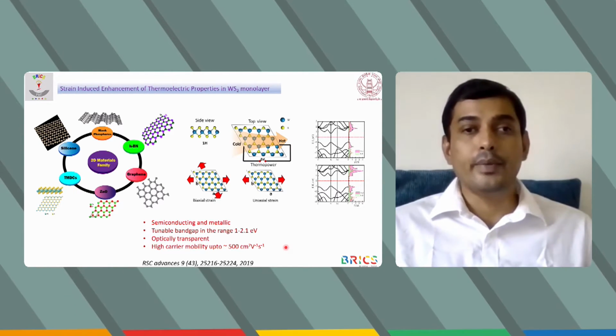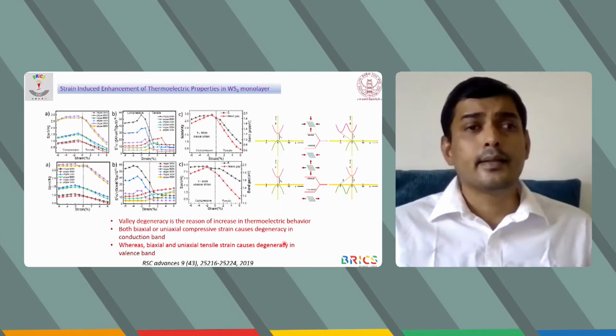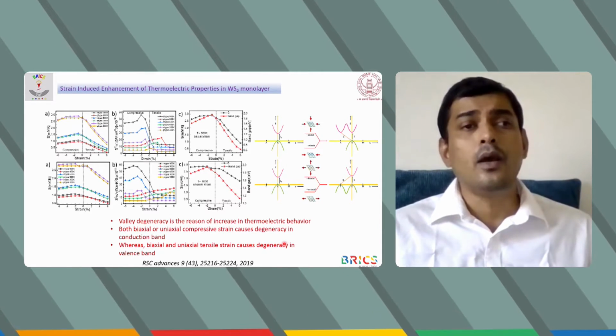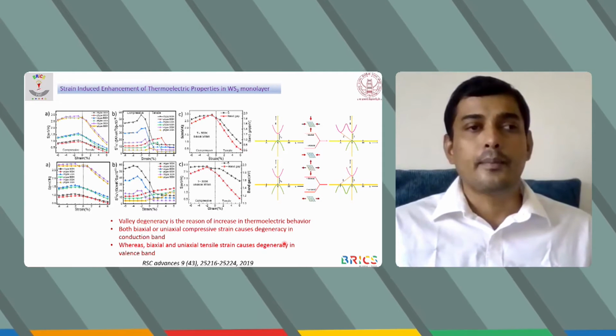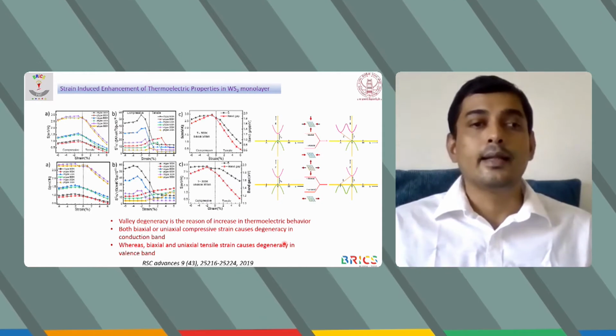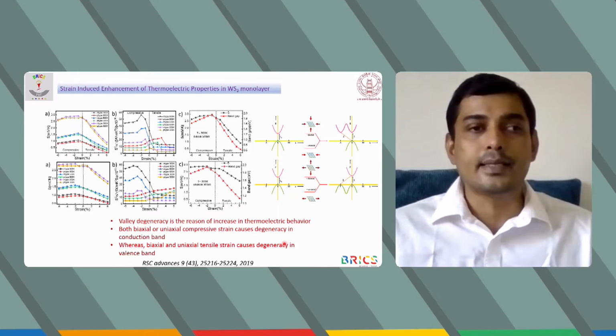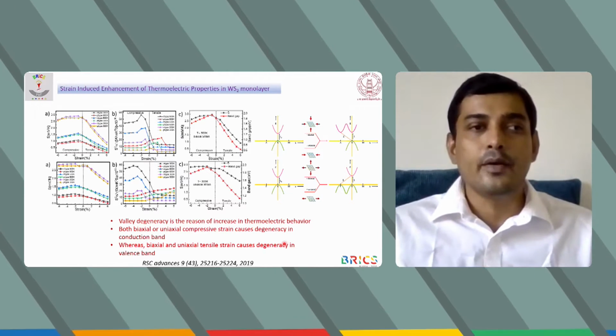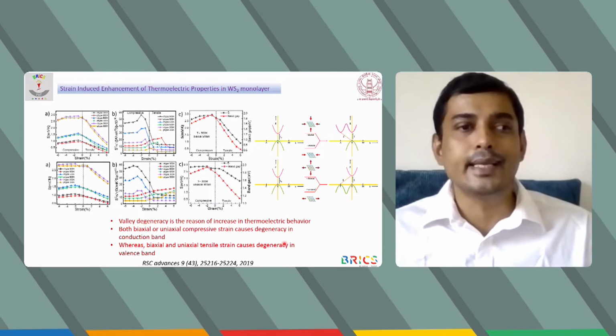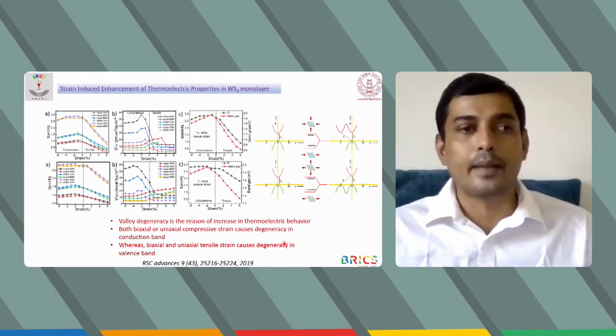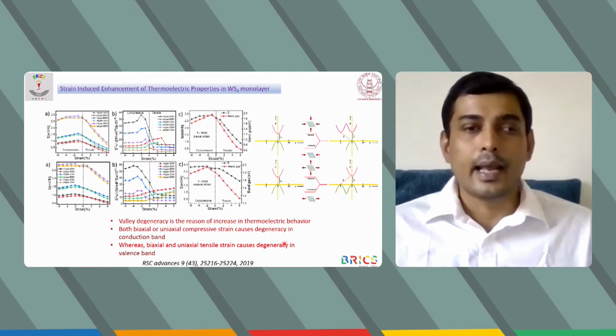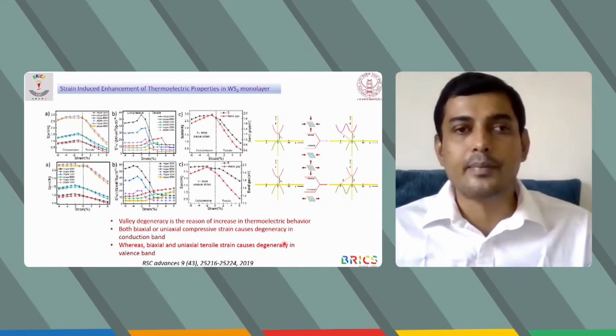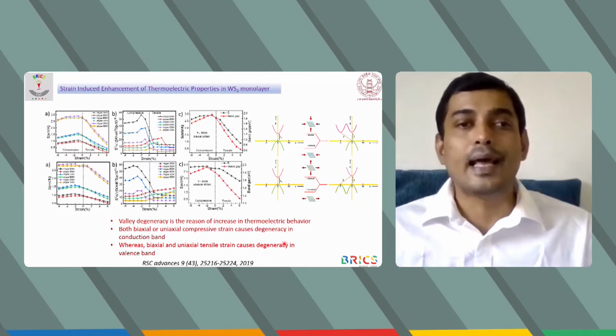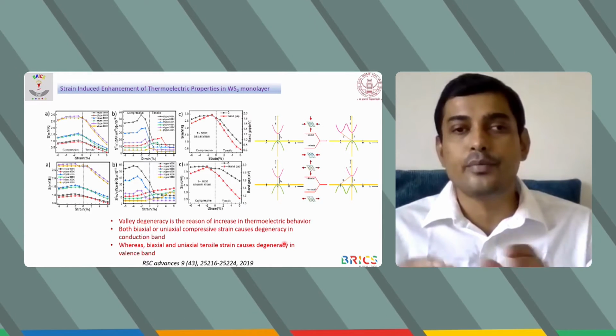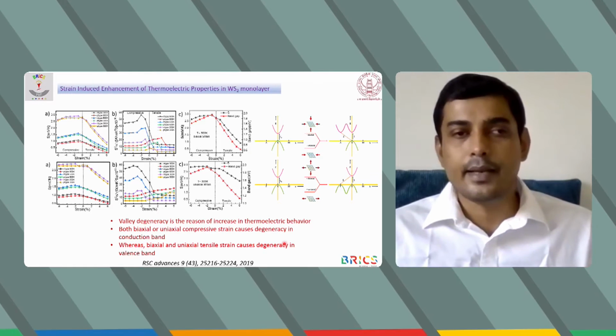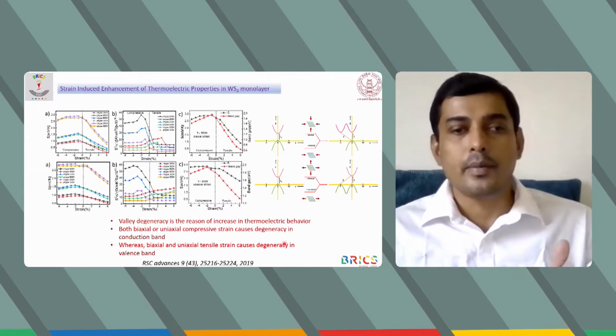And when we studied the effect of strain on the WS2 at different temperatures, we found that the thermoelectric parameters are responding differently with the increase or decrease in temperature. And with decrease in temperature, we found that the thermoelectric parameters are showing better results. And we try to explain this behavior by using the valley degeneracy of conduction and valence band when we were applying compressive strain and tensile strain to our material.